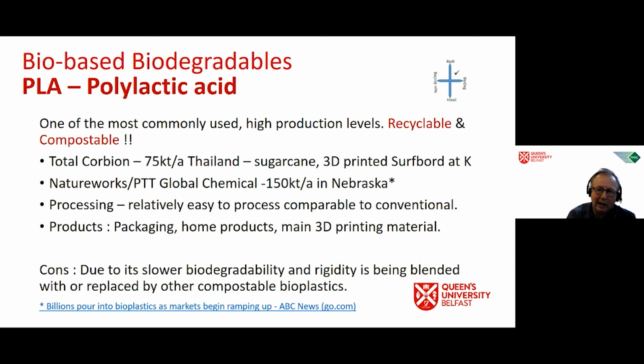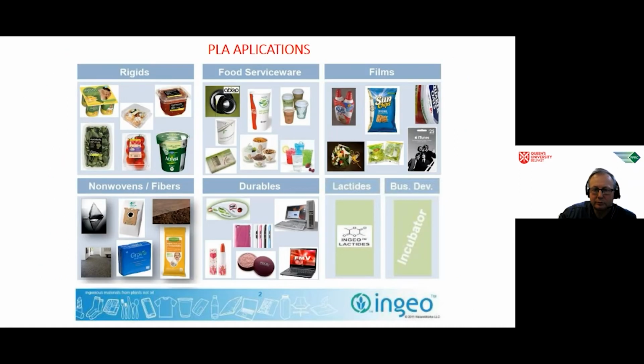A disadvantage of PLA is that it decomposes relatively slowly in composting sites, and it's a fairly hard, clear material, which I've already mentioned. However, it is being commonly blended with more flexible and compostable biomaterials to make the PLA much more usable. It's still a very common material, which is on the increase. That slide is from NatureWorks, just an example of some of their products. I won't dwell on that slide too much, but you can see typical rigid products, typical flexible films and nonwovens. For 3D printing, the default filament is PLA, so most people would use PLA if they're designing for 3D printing.